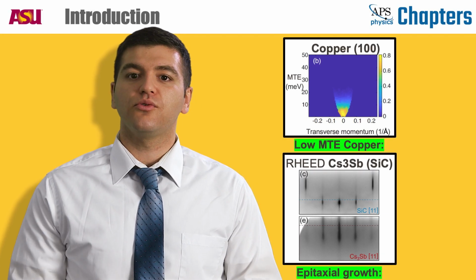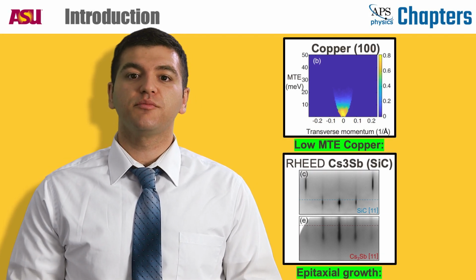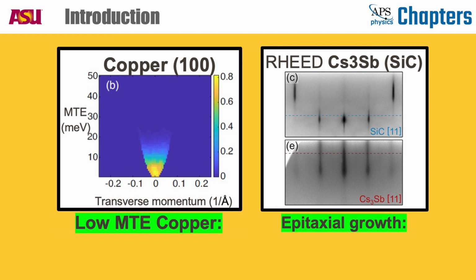Well, in the surface sciences world, they already exist, and they have been tested at low voltage. The single crystal ordered surface of copper 100 produced a world record low MTE of 5 millielectron volts at cryogenic temperatures at threshold, albeit with low quantum efficiency.